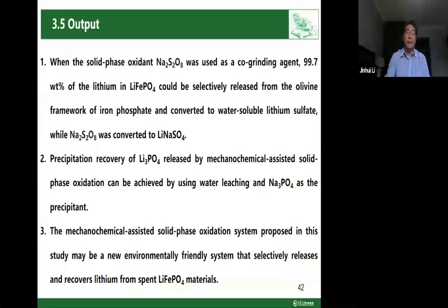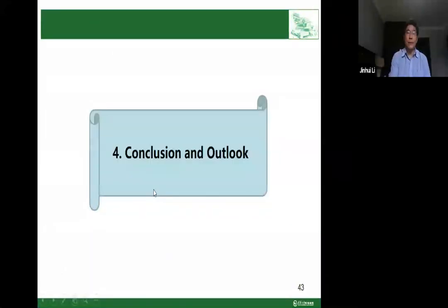The second one is precipitation recovery of lithium released by mechanochemical assisted solid phase oxidation, which can be achieved by using water leaching and sodium phosphate as precipitant. The third one is that the mechanochemistry assisted solid oxidation system proposed in this study may be a new environmentally friendly system that could selectively release and recover lithium from spent lithium iron phosphate material. So we can very briefly conclude the presentation.